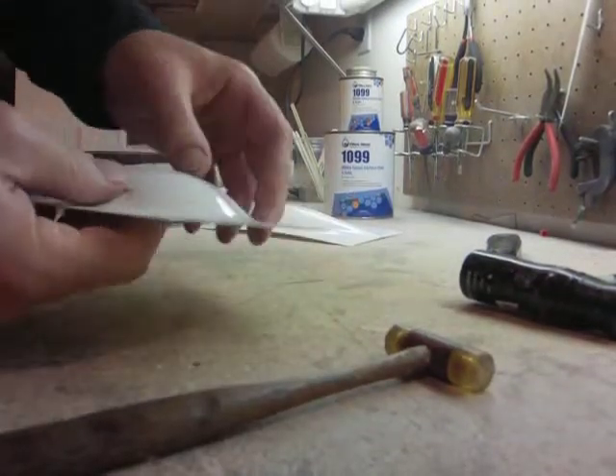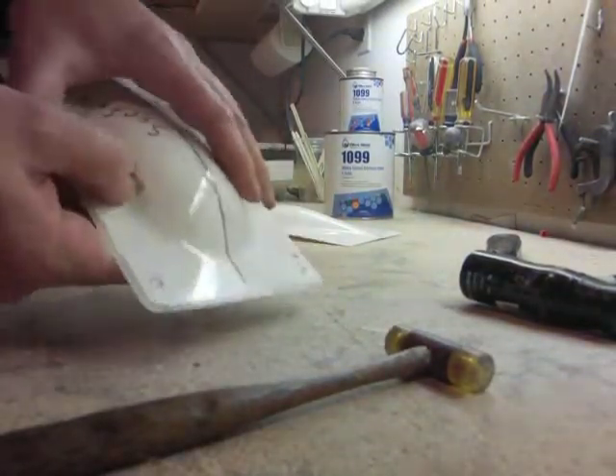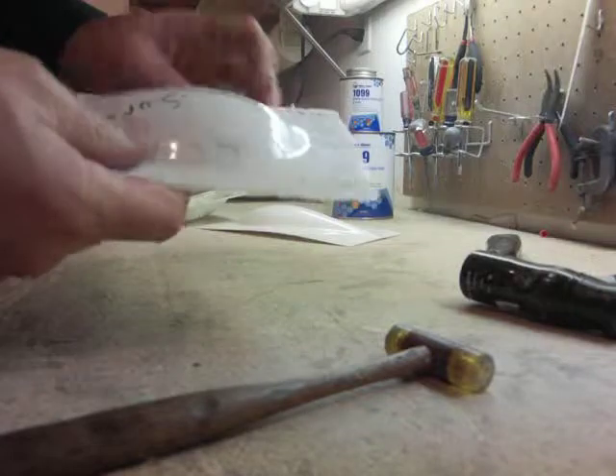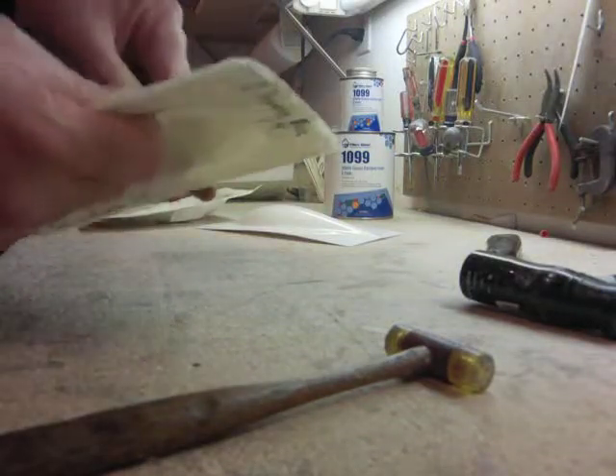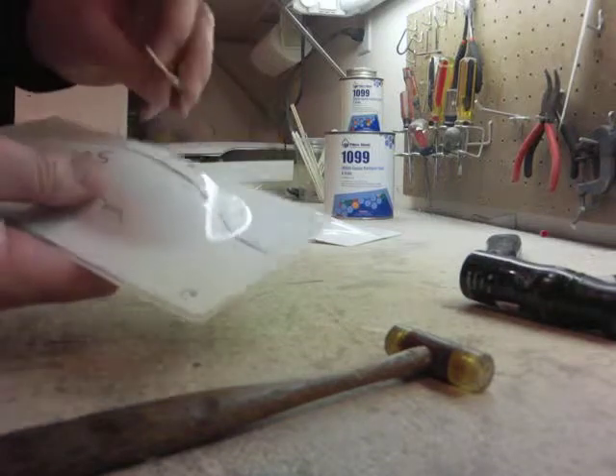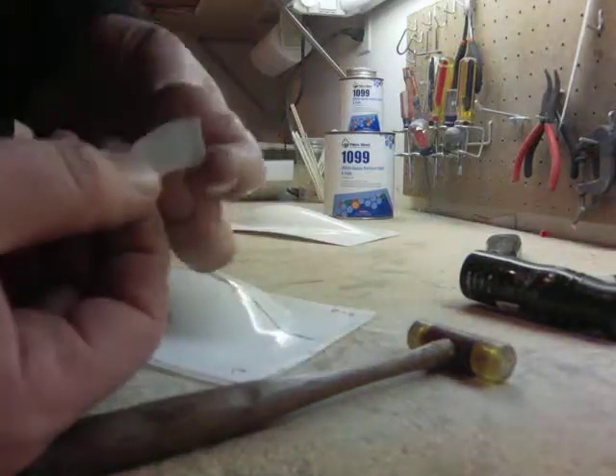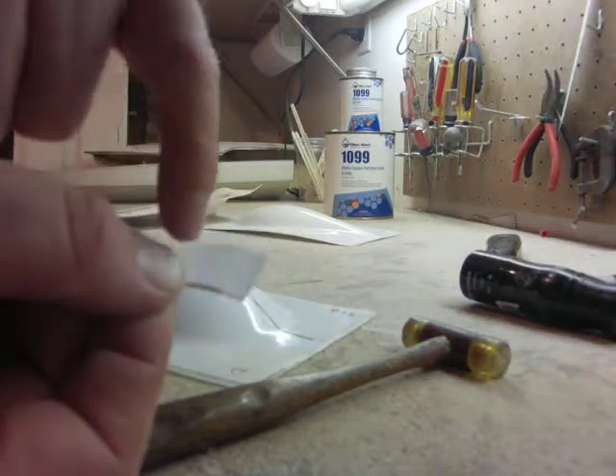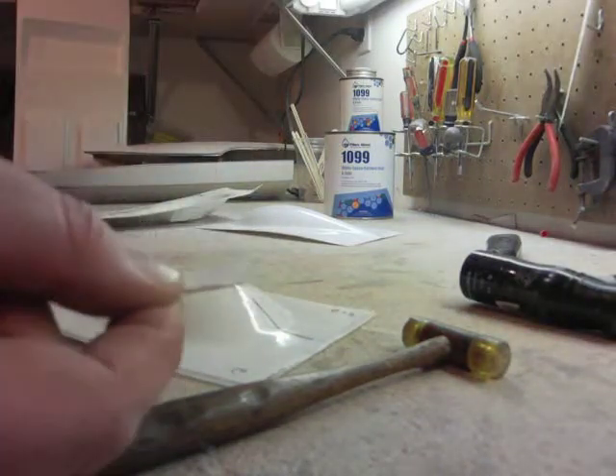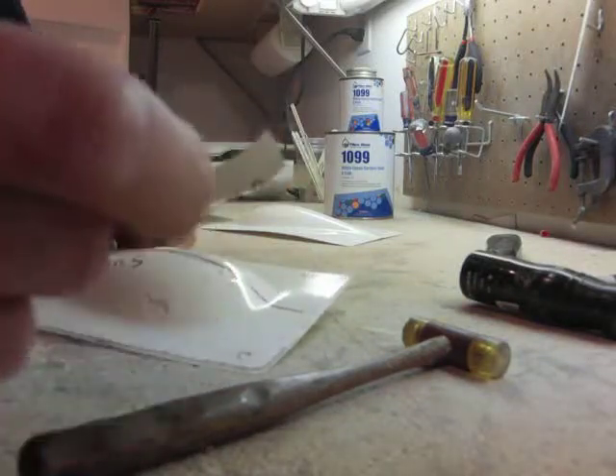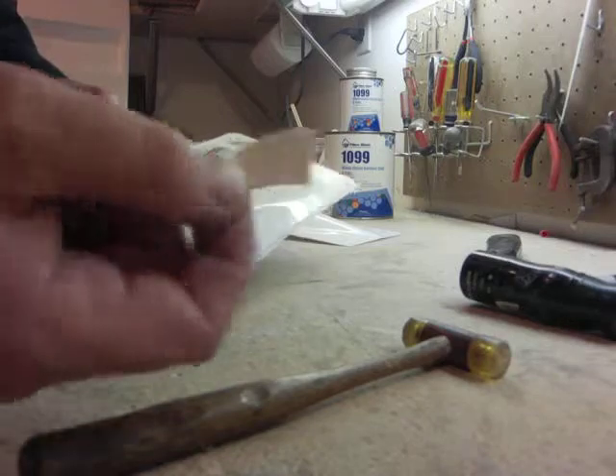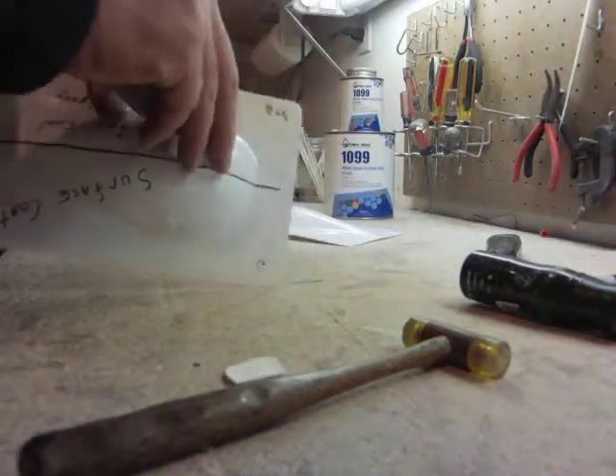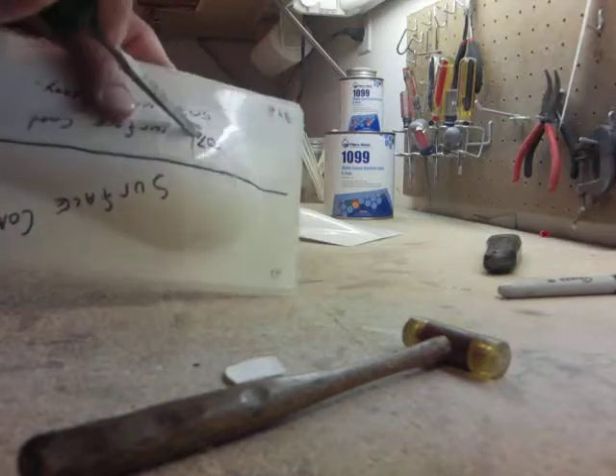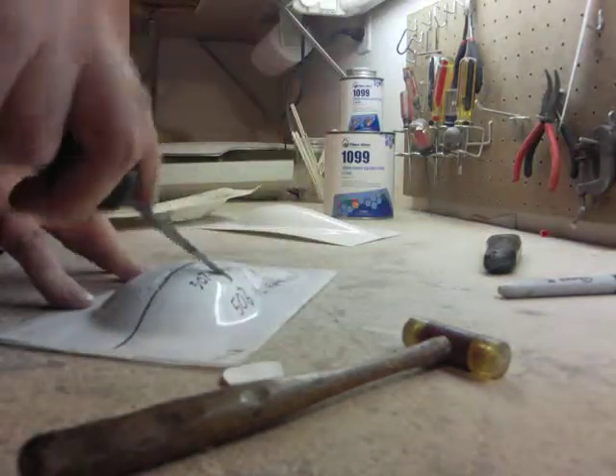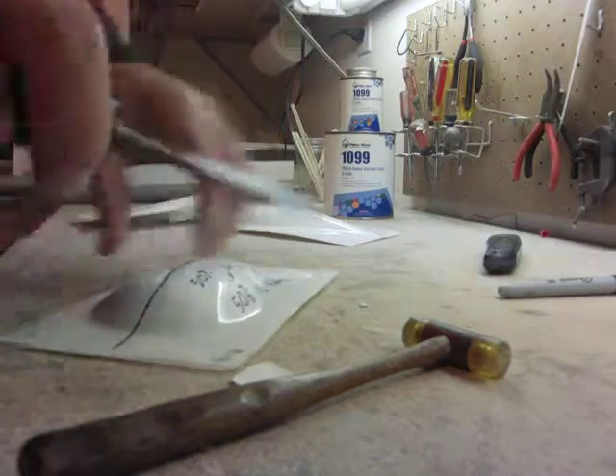Okay, that's a pretty hard hit. Boy, smacked through it right there. Actually fractured it. See the inside, you can see the cracks. Cracked the hard surface coat. Hey, look at that. I don't know if this will show up here or not, but you can actually see the imprint of the glass pattern. So it had good adhesion, but that tooling coat, that was the 50% surface coat, 50% epoxy, will separate off. Obviously not real easy, but that was crushing the glass from behind it.